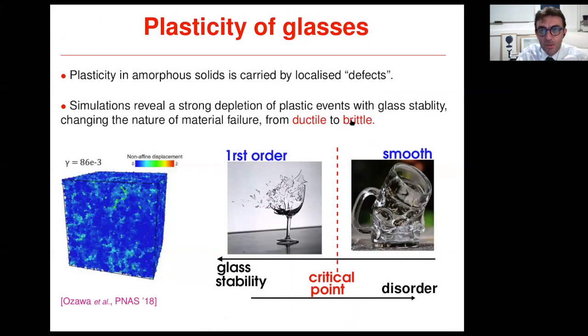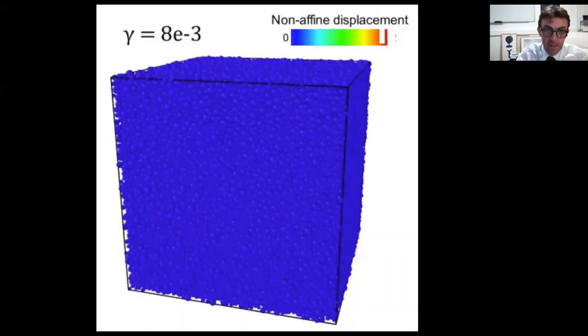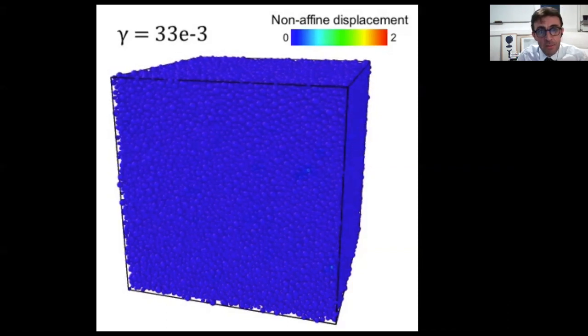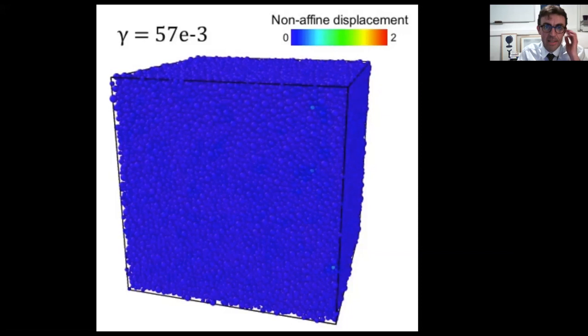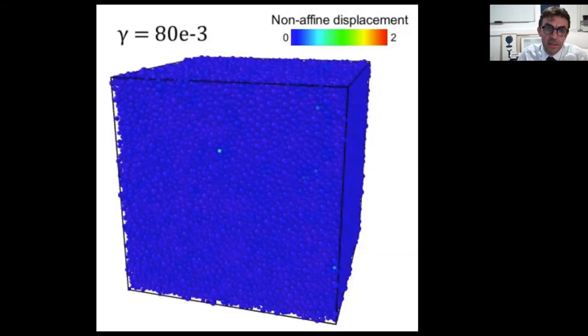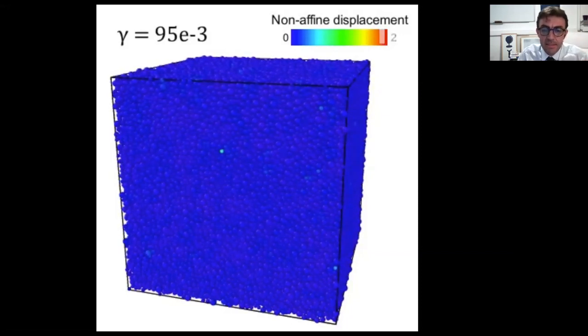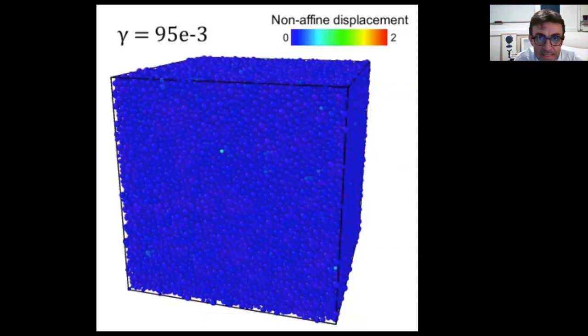I will now go to a very stable system, and I will show you how this system is deformed. So this is the initial state of the system. So it's very deep blue at the beginning when nobody has relaxed. I deform that system quite a bit more, and I will stop later. So I stop here, for instance. So we see that we have deformed that glass quite a bit. And by contrast to the system that was full of defects, almost nothing happened here. It's still a deep blue, almost elastic system.